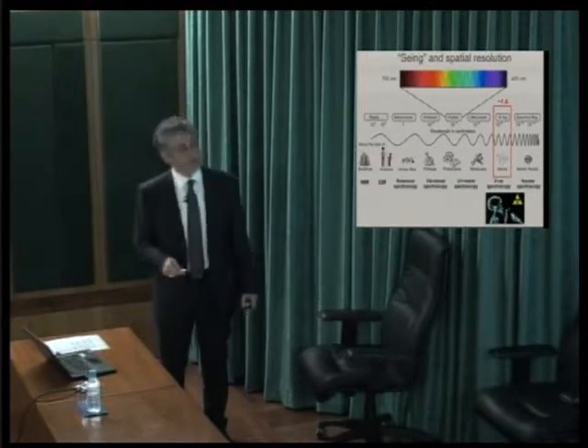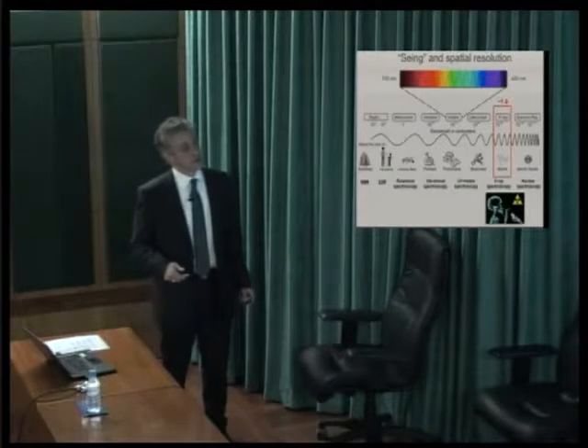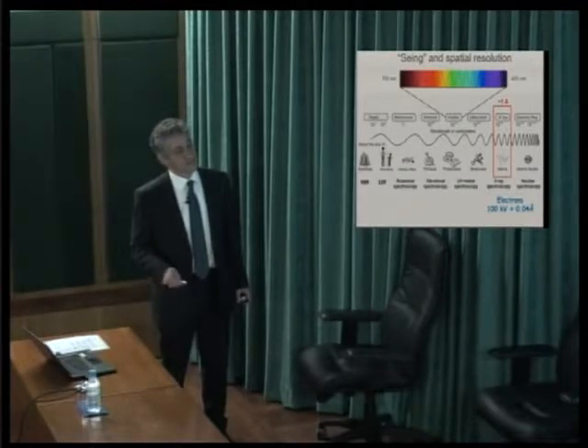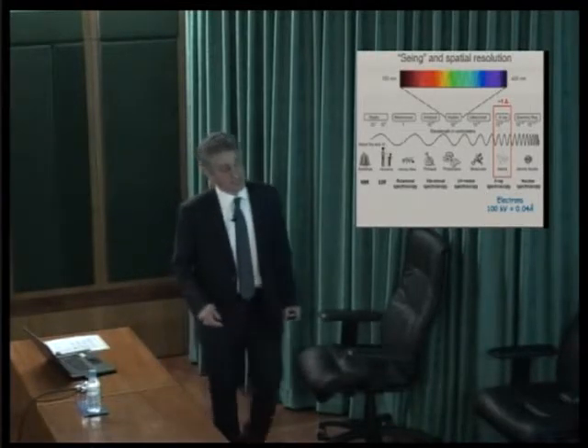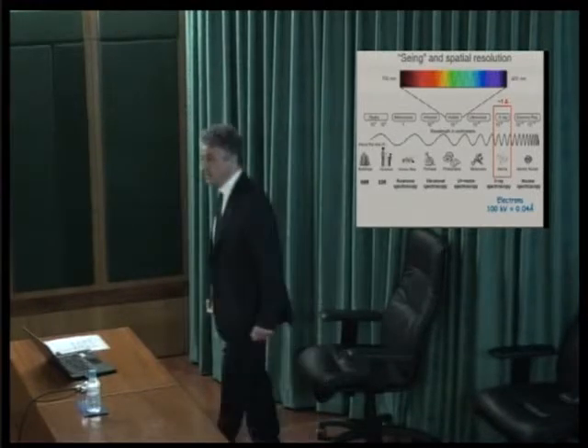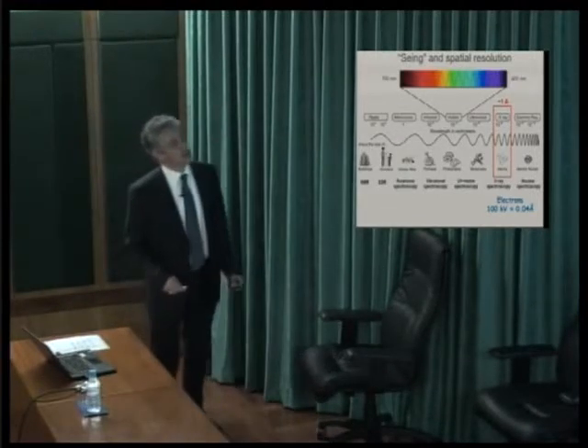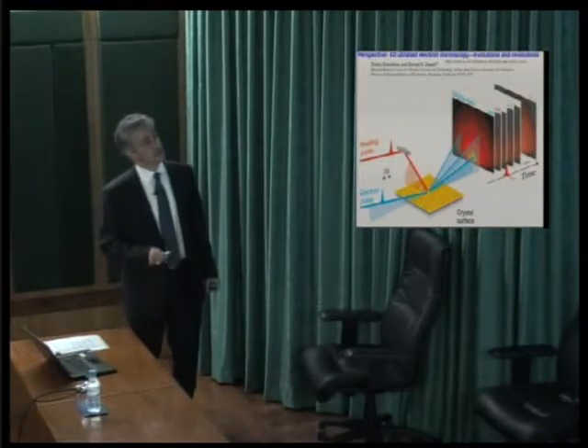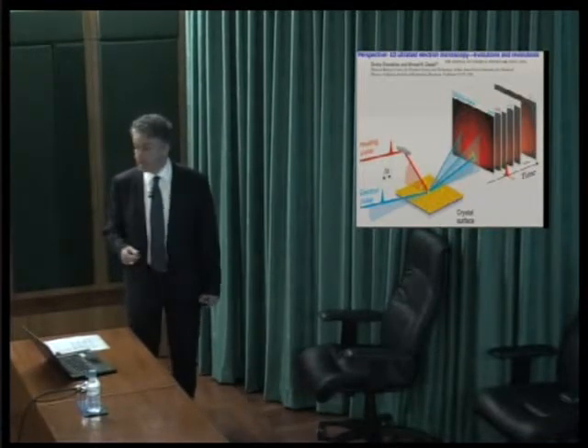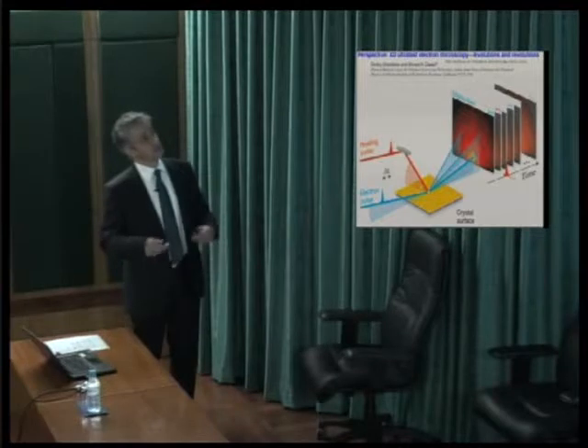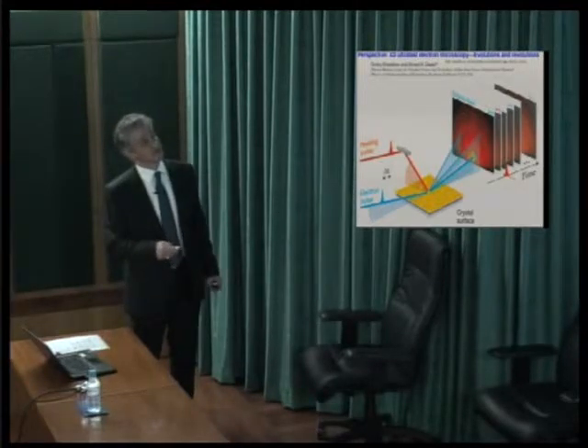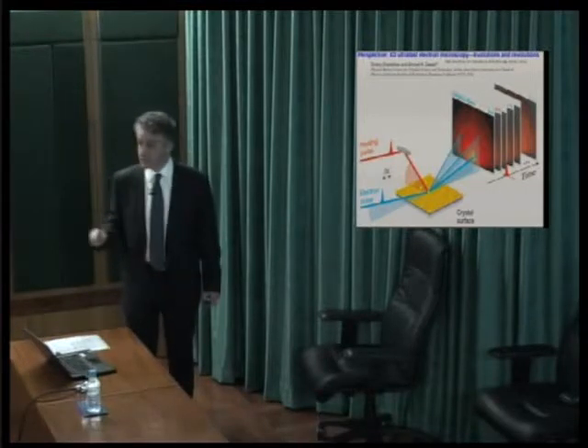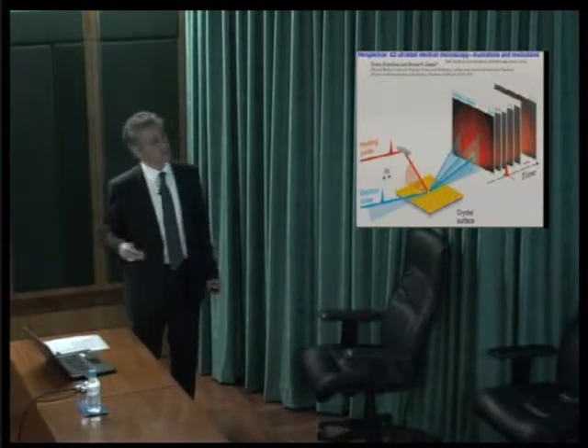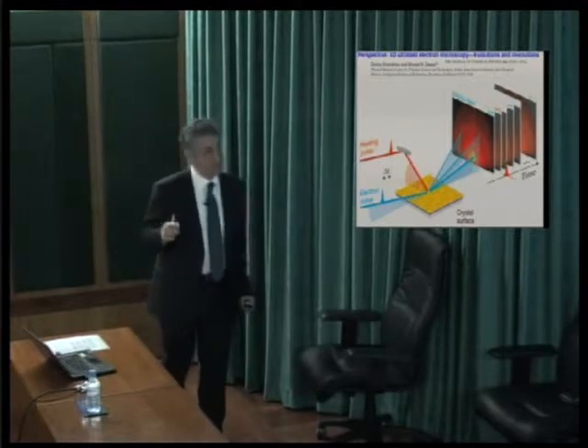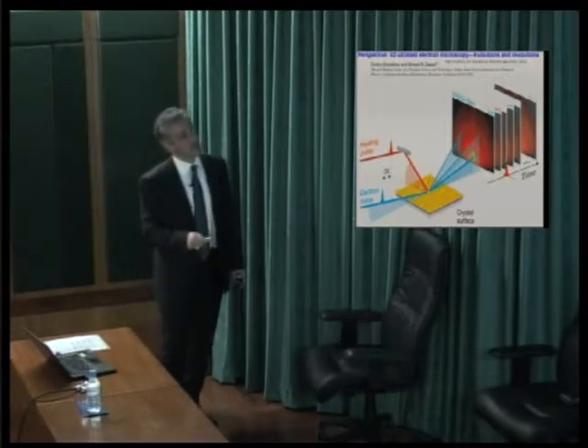And in order to then see structures, you have to go to the short wavelength range, to about one angstrom resolution. Or you can also use accelerated electrons, 50 to 100 keV, and do electron diffraction. And Ahmed Zewail actually pioneered the field of femtosecond electron diffraction, and then he even brought it to a new level with ultrafast electron microscopy, and he calls it 4D because you can see in the three dimensions of space, in real space, not in Fourier space, and in the dimension of time.